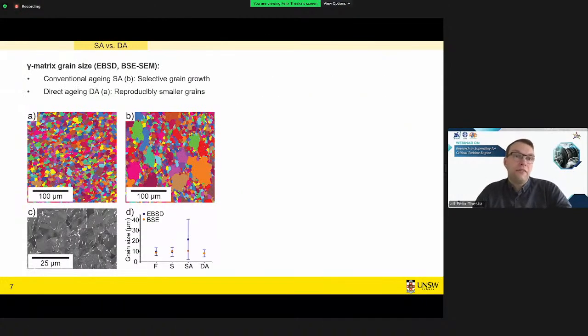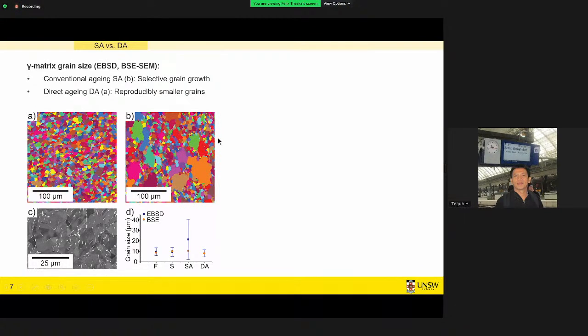Starting with the grain size, I used some EBSD and electron microscopy to have a look at the grain size, and we see that after direct aging, the grain size remains very small, whereas after the conventional aging, we find some selective grain growth occurring here and there.